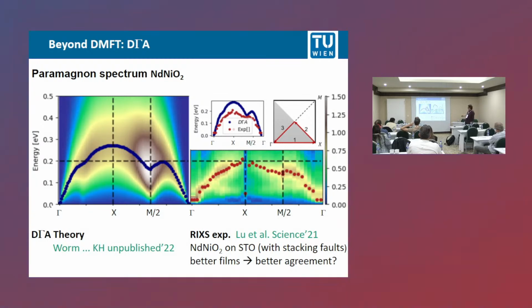spectrum. Here you see the maxima of the experiment in red, in theory in blue, and it is giving a very reasonable agreement. So the experiment is a little bit lower. That means the antiferromagnetic exchange, J, is a little bit lower. But remember, it's still here the films with stacking faults.